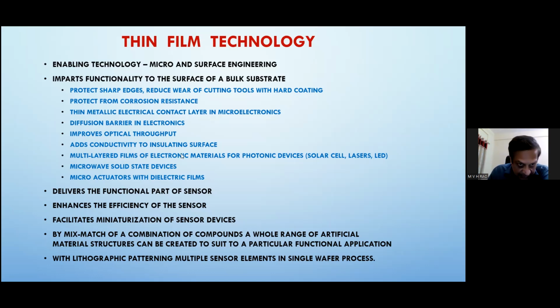And also in the case of certain insulating surfaces, we want a top conducting layer like ITO on Kapton, which is one of the activities we have done, a transparent conducting layer on a polymer sheet that avoids electrostatic discharge. You see, an insulating surface gets charged. Ultimately, after some time, there will be electric discharge. But if there is a conducting layer, it will disperse the charge uniformly over the surface, and that way we can avoid electrostatic discharge. ITO is applicable to all the video screens also. I think most of the mobile screens are also coated, because it is conductive as well as transparent.